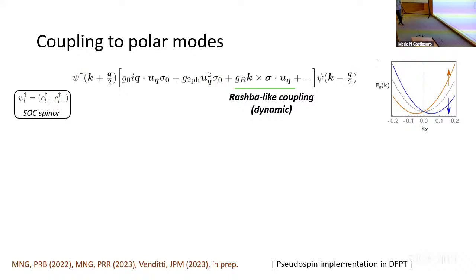And this is a spinor. So you can have the typical, the usual electron-phonon coupling, Q·U with sigma 0. So it's the same for both, say, pseudo-spin up and pseudo-spin down. But I said that this is a transverse optical mode. If it's transverse, it means that these two things are perpendicular, therefore it's not allowed. Then you can say, okay, let me go to the next order, that is quadratic. This is very exotic. It turns out that in these systems this can be relevant, but it's not what I'm going to discuss today.